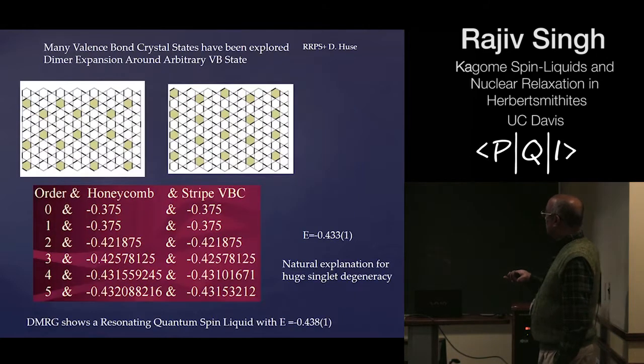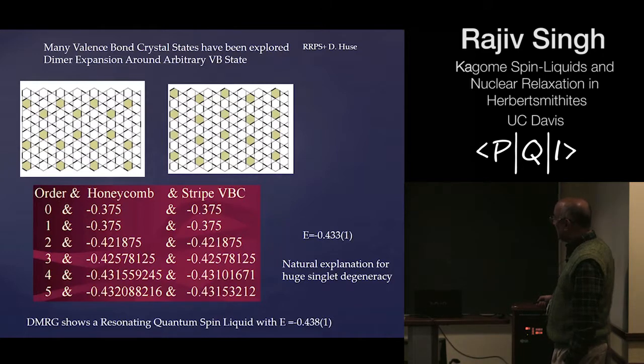So I think I'm running a little bit late. Maybe I could just say that the one thing that we tried was basically an expansion again, because there are a huge number of singlet states. You can start from different kinds of valence bond configuration and try to calculate the energy around any one of them, and what you find is that essentially you get very close energies, and not too far from what was anticipated to be the ground state energy at the time, of the numbers that we were getting. But more recent DMRG studies clearly show that this valence bond singlet state is not the correct ground state, but the correct ground state is a resonating quantum spin liquid state, which has an energy even lower than this.